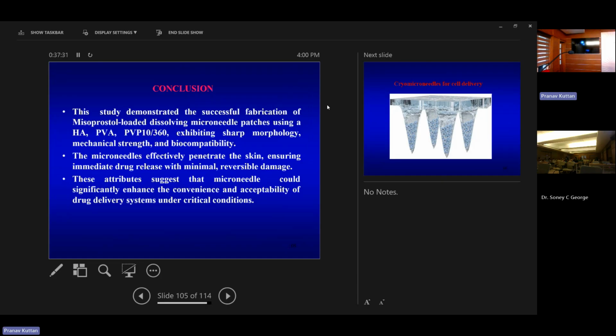So the conclusion is that this study demonstrated the successful fabrication of misoprostol, the drug we chose, as dissolving microneedle patches. It exhibits a sharp morphology, which we could see using SEM. It efficiently penetrates the skin, ensuring immediate drug release, because from the drug release study we could see that it was releasing within the first 2 minutes itself. Then the reversible damage only is happening. It is very minimal. And this suggests that this microneedle could be used for convenient and acceptable drug delivery in critical conditions because it releases very quickly.